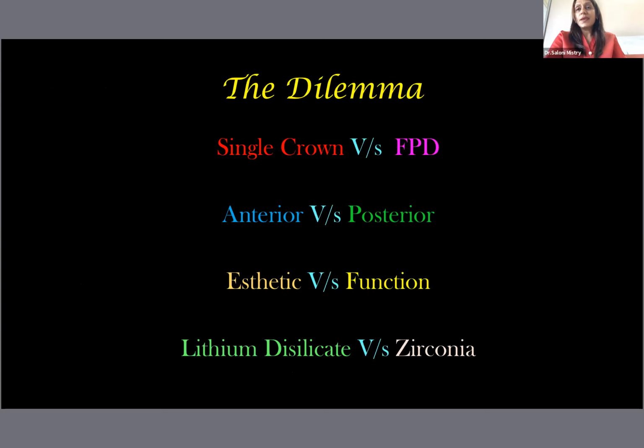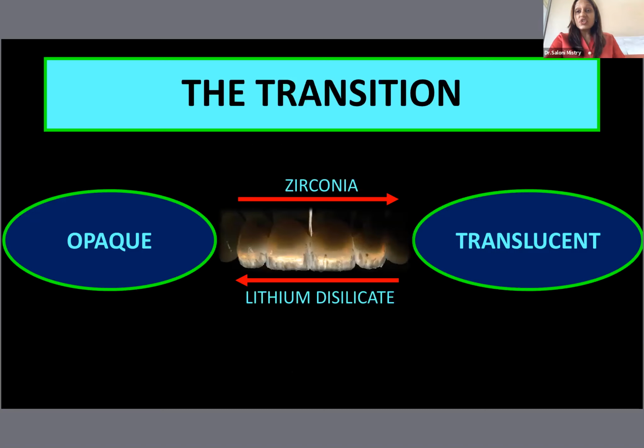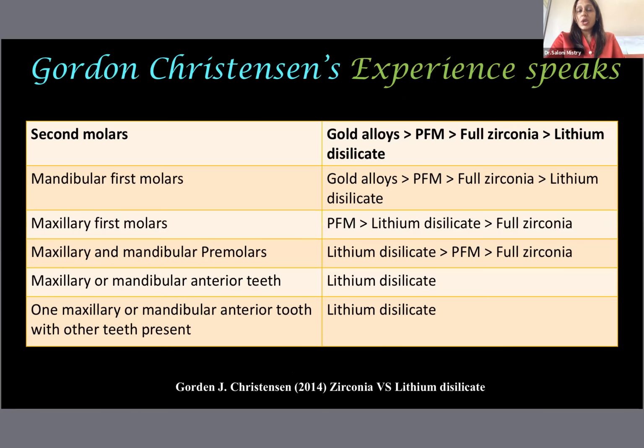So what's our dilemma? Single crown versus a fixed dental prosthesis, anterior versus posterior zone, aesthetics versus function, lithium disilicate versus zirconia, stronger versus weaker, opaque versus translucent. Gordon Christensen, the Dean of aesthetics, says that particularly in the posterior zone, he still prefers precious alloys. If you see, gold alloys, then PFMs, then zirconias, obviously not lithium disilicate. And when it is the anterior zone, then obviously lithium disilicate is your material of choice. But all these have to be used very judiciously.